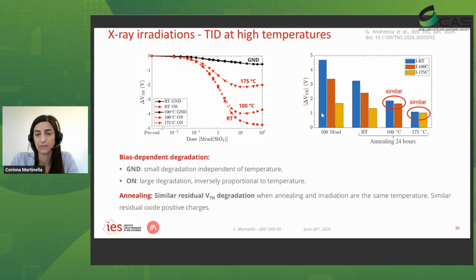So these are the results of our degradation of the threshold voltage after the irradiation. We have here in blue the device exposed to room temperature, 100 C in orange, and 175 C in yellow. Here is the annealing for 24 hours at room temperature, so things get a little bit better. And then we have 24 hours at 100 degrees C and 24 hours at 175 C. So if we compare the device that was irradiated at room temperature and annealed at 100 C with the device that was irradiated at 100 C and annealed at 100 C, we see that things are pretty much similar. And the same happens for the annealing at 175 together with the device irradiated at 175.